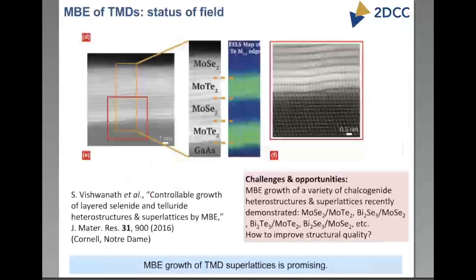One of the big advances made recently in the literature is this beautiful paper from Cornell and Notre Dame that shows that just as superlattices were developed in the semiconductor world for many, many decades, one can at least have some expectation that we should be able to do this with MBE. The results from Cornell and Notre Dame clearly show that even though there are still imperfections, and the interfaces are wavy and things like that, nonetheless, people are starting to get a handle on how to make complex superlattices with these TMD materials. And they've actually explored quite a range of different combinations that I've listed here on the slide, anything from bismuth selenide, molybdenum diselenide to molybdenum selenide, molybdenum telluride kinds of superlattices.